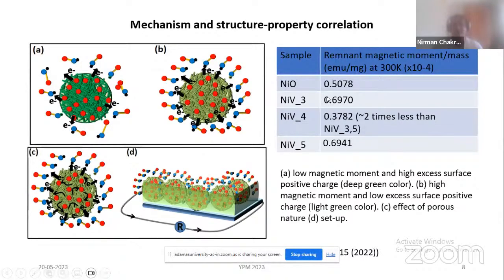This is not the case for NiV3 and NiV5, which first of all have a greater remnant magnetic moment. Although they attract a greater number of nitric oxide molecules, there is a problem of mutual repulsion on the hugely crowded surface full of nitric oxide molecules, because of which the effective interaction gets hampered. Secondly, because the domains are not flexible, even after desorption occurs, the system retains its magnetism, so the surface gets overcrowded and the recovery is definitely less. So even if it's a soft ferromagnet, the amount of softness matters.